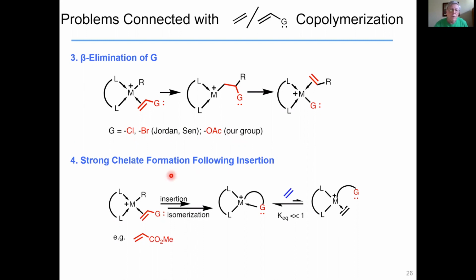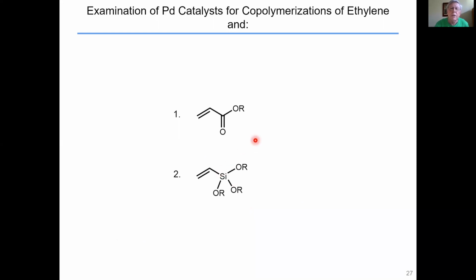The other issue is that we can generate a fairly strong chelate. So this comes about particularly with these vinyl esters. If that vinyl ester inserts, the ester carbonyl group coordinates back to the metal center, and then you're faced with displacing that interaction with ethylene to propagate the chain. And that equilibrium can lie very far to the side of the chelate. So I'll just show you how this works with methyl acrylate, and then move on to our study with the trialkoxysilane. So we'll talk briefly about copolymerization of ethylene and methyl acrylate.